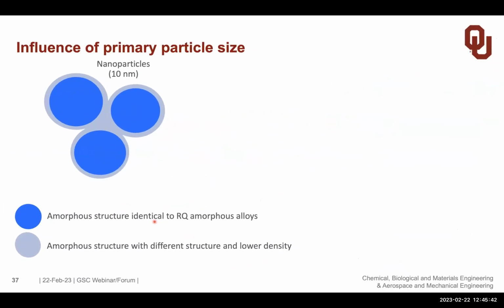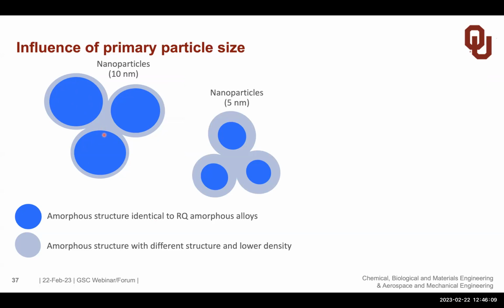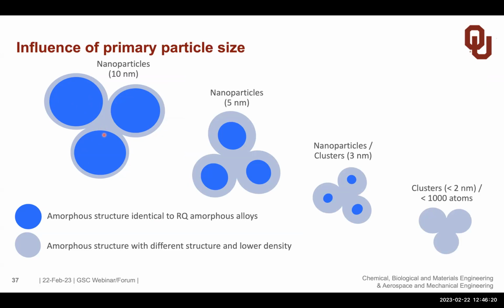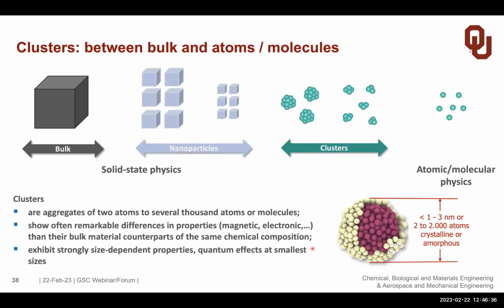So one approach was now, if we have a new amorphous phase, could we also make a material which has 100% of that, which would now be a different amorphous material. And so the idea was, what I described to you was happening in particles of about 10 nanometer, and then we consolidate it. And then if you would decrease the initial particle size, the fraction of interfaces would go up. So we would get more and more of this light blue interfacial regime. And the question is really, can we get 100% if we take very small clusters of this material? And up to today, I don't have the answer, but we know we can produce much more of this interfacial regime if we go to a different approach, how to make the clusters.